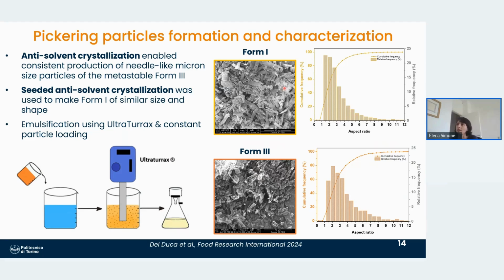So we did reverse anti-solvent crystallization. We had our solution of curcumin in ethanol, put it in a big beaker of water, and then mixed very quickly to create uniform supersaturation very fast and get relatively uniform size and shape distribution of form 1 and form 3. For form 1, we had to add a little bit of seeds of form 1, so we did seeded anti-solvent. And we got two different polymorphs with very similar shape and size distribution.